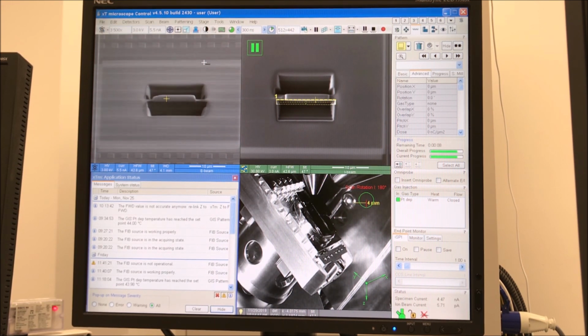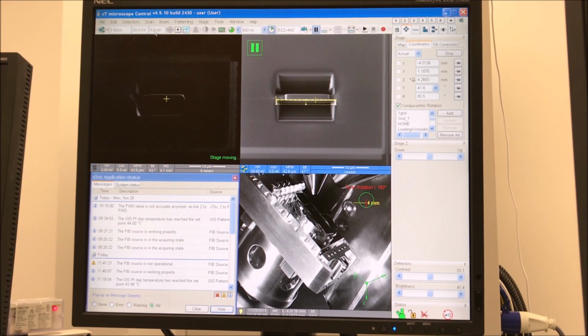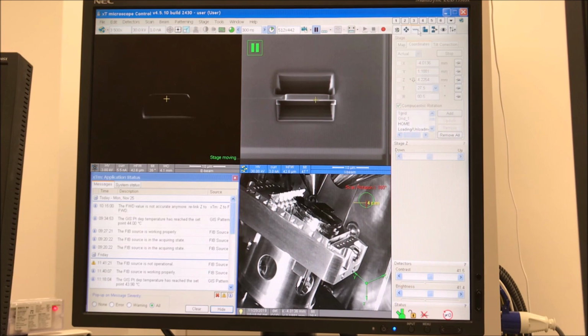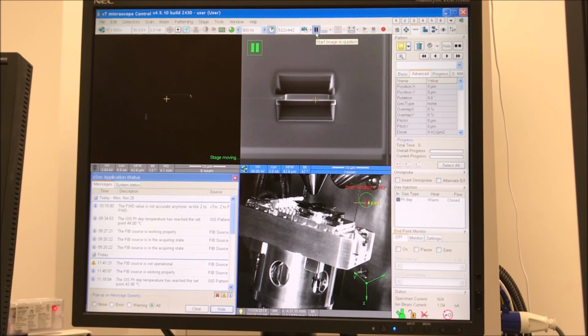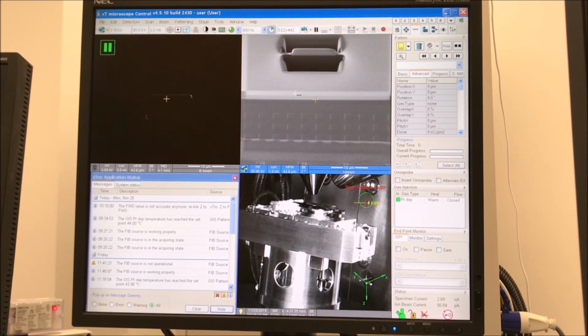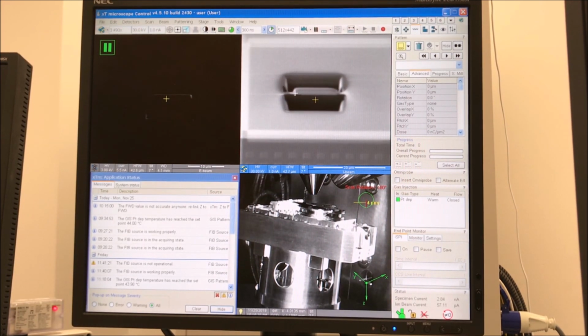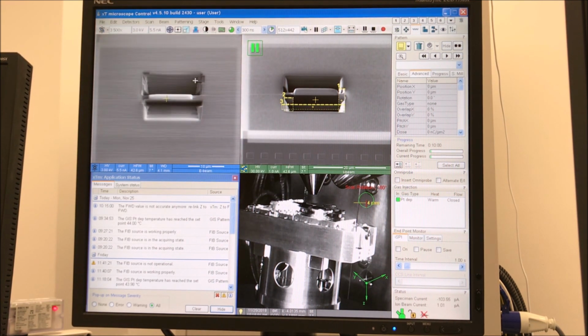And so once this is done, we will now move to undercutting the lamella. So for that, I'm tilting to 7 degrees, and I changed my ion beam current down to 1 nanoamp. So once it's at 7 degrees, I can go live, and you can see the lamella isn't centered anymore. So I'm using the shift knobs on the MUI to recenter it, and now I'm drawing 3 rectangles in a lopsided U, or what some people refer to as a J cut. I changed the pattern order to what's called parallel, meaning all 3 are executed at once.